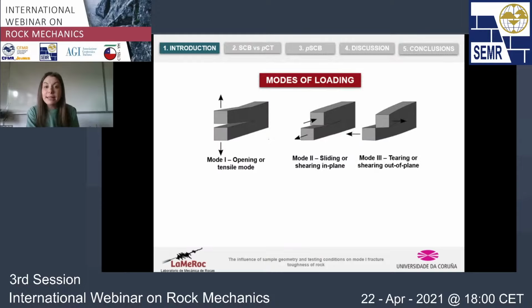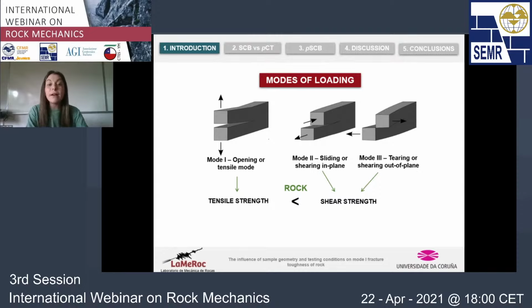In fracture mechanics, there are three modes of loading. The first one, the one that you can see on the left, is mode 1. In mode 1, the crack face is open perpendicular to the crack plane. For this reason, this mode is also called the opening or tensile mode. In the other two cases, in mode 2 and mode 3, the crack faces slide in the crack plane due to a shear stress. But if we focus on the case of rock, which is the material that we are studying, as all of you may know, the tensile strength is comparatively lower than the shear strength or even the compressive strength. So for this reason, mode 1 fracture toughness is the most studied parameter in rock fracture mechanics.